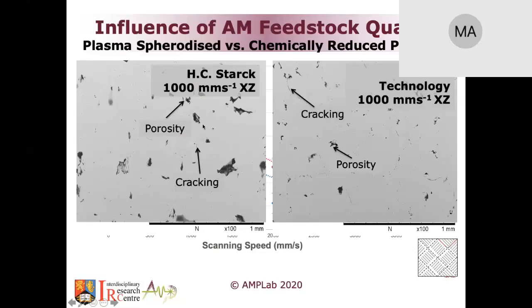And that was, I think, the key contribution we made, and that's where reality is in additive manufacturing. We can try to seek a material that doesn't have cracks, doesn't have pores, the best quality possible. The question is, we sometimes end up over-designing what we want. If we need a structure that is only there as a shield against the X-rays, then we don't really need to increase the cost of the process by using high-spec powders to do a job which can be done with the low-cost powder.